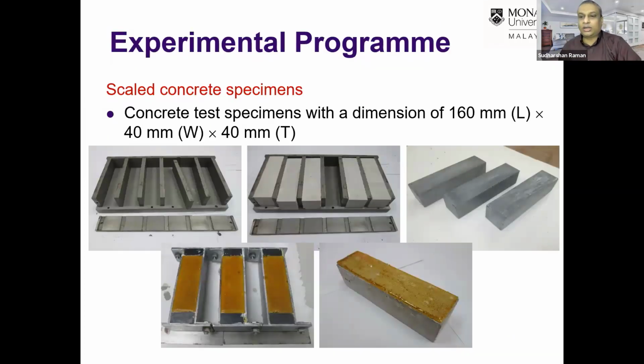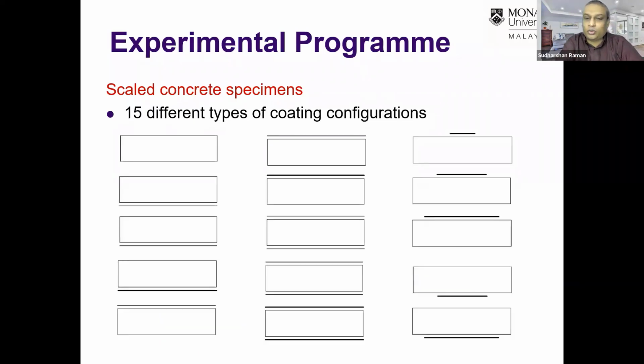And then in the next stage, what we did was lab scale experiments using concrete specimens of 40 by 40 by 160 millimeters, where we developed these specimens using fine aggregate as well as coarse aggregate of 10 millimeters, and then we applied the polyurea coating, the formulation PU6, with different coating variations as shown. We tested 15 different coating configurations as shown here. We varied the coating location, coating thickness, as well as which surface they are coated.